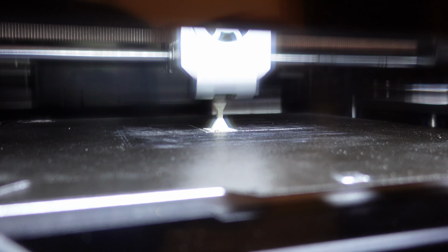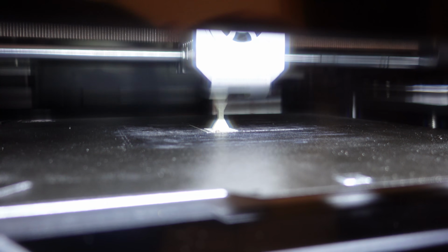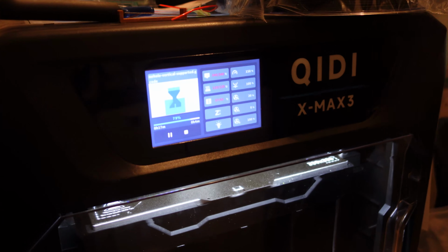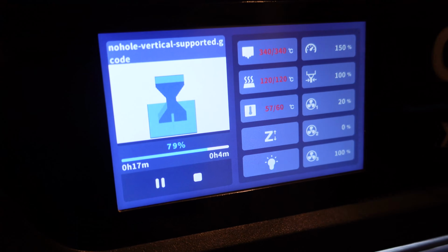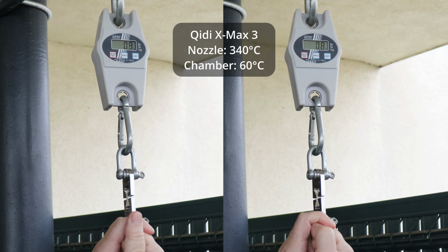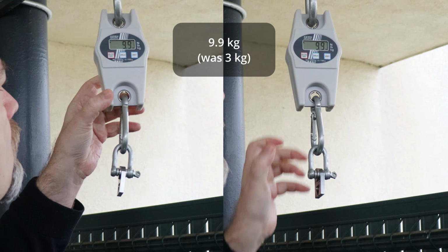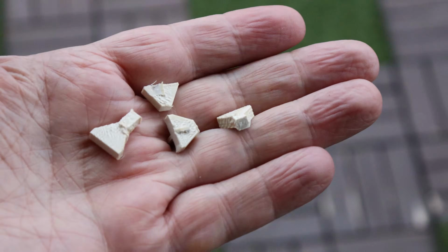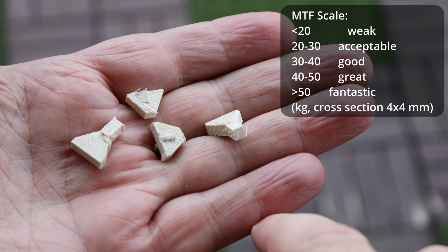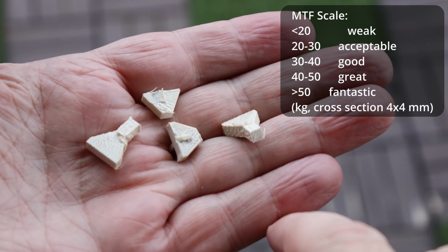I need one more test. I reprinted these vertical test objects on the Qidi X-Max 3 at 340 degrees Celsius and a 60 degrees Celsius actively heated chamber. 9.9 kilograms. This is a significant improvement, but this is still weak. With this size of the test objects, the break load should be about 20 kilograms.